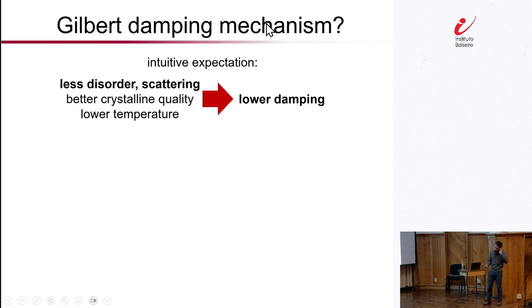So again, drawing this analogy between magnetic damping and mechanical friction, imagine if you have a material with, let's say, a very rough, messed up surface, you tend to have a higher friction, and on the other hand, if you have a nice smooth surface, you tend to have lower friction. So we might expect something similar out of this magnetic damping as well. So you might say that we should get lower damping if you have a nice clean material with less disorder and not a whole lot of electronic scattering. And this kind of simple intuition does seem to make sense in light of, again, the simple physical picture.